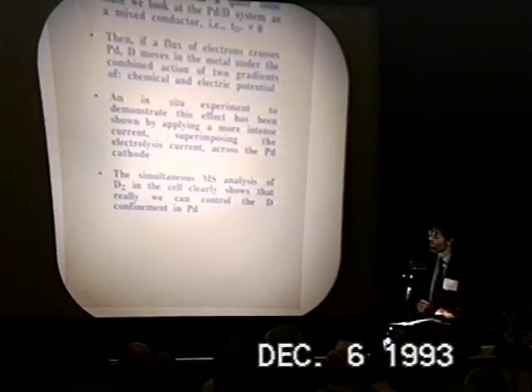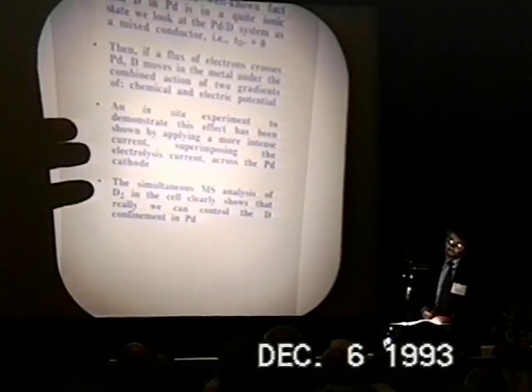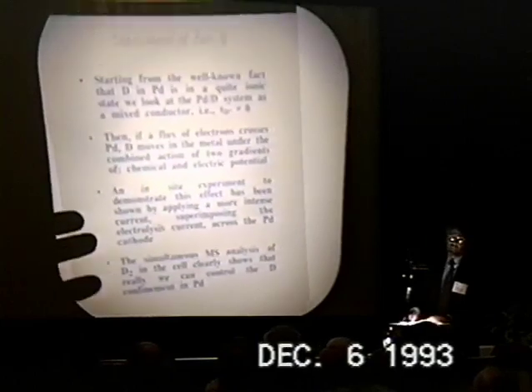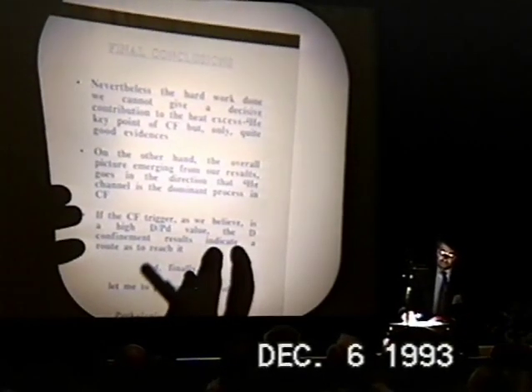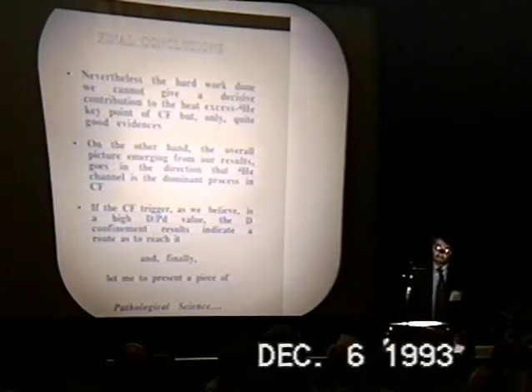The simultaneous mass spectrometric analysis of the deuterium cell clearly showed that we can really control the deuterium confined to palladium. And the final conclusions are, nevertheless, we have work to be done. We cannot give a decisive contribution to the heat excess helium-4 key point of cold fusion, but only quite good evidences. On the other hand, the overall picture emerging from our results goes in the direction that the helium-4 channel is the dominant process in cold fusion.